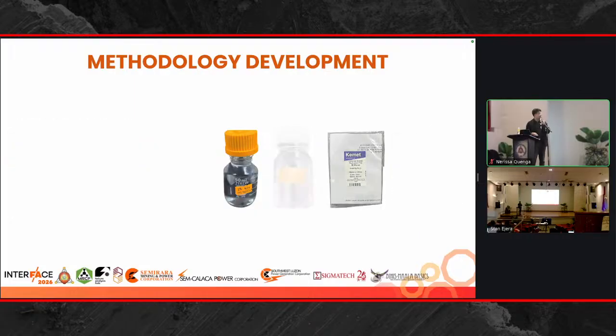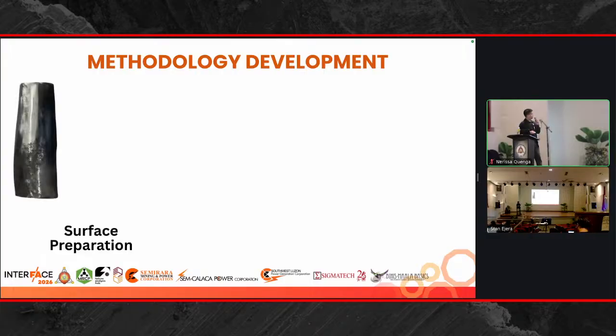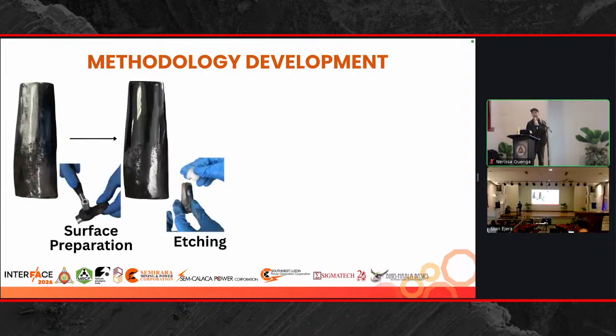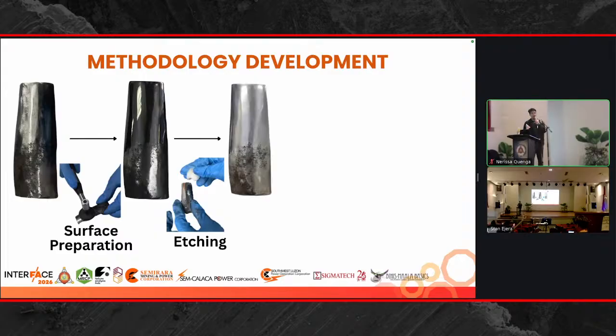The steps involved in the in-situ metallography are initially just the same as the actual metallography. We have surface preparation to clean the surface and remove the scratches. We have the etching to reveal the microstructure. But it gets different past this point, because we need to replicate the microstructure that is revealed after etching. So we do replication.